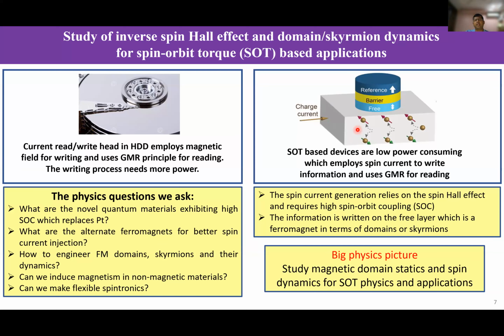And that spin current can apply a torque on this tunnel junction, where we can play around with this free magnetic layer. Depending on its orientation, which will be either parallel or anti-parallel to the magnetization of the reference layer, which is another ferromagnetic layer where the magnetization is more or less fixed, we can use it as a hard magnetic layer. You can fix it using exchange bias. That means you can deposit an antiferromagnet.